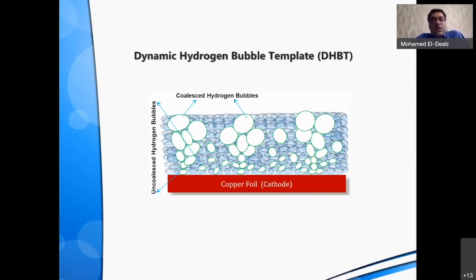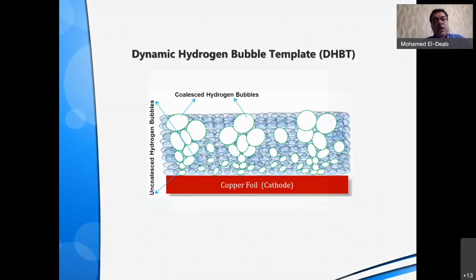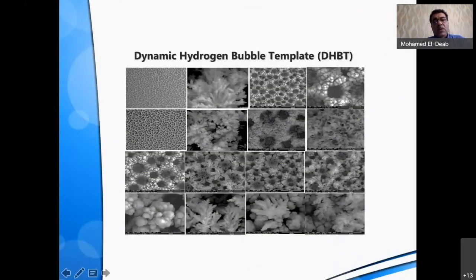Here we used a technique called the dynamic hydrogen bubble template technique, which is used to deposit a porous metallic layer atop a substrate like copper foil. In this case, we produce intensive hydrogen evolution simultaneously with metal deposition. The produced gas bubbles act as a template for the metal deposition. So we ultimately can have porous structures like this, and we can modify these porous structures by deposition in the presence of some additives, or further modify them by doping with other metals.